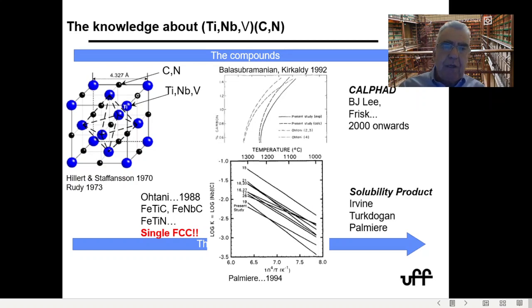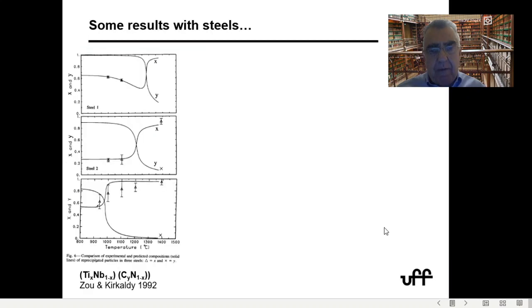So this continues with many assessments in the CALPHAD method and much work in the solubility product arena, mostly Irvine, Turkdogan, and Palmieri. If we look at some results that were obtained with steels, we see Zou and Kirkaldy, for instance, measure very carefully in titanium-niobium containing steels. They showed very clearly that there was compositional variation depending on the temperature. So the carbides were not really titanium nitride and niobium carbide as we would like to think, which is very simple, but they were much more complex.